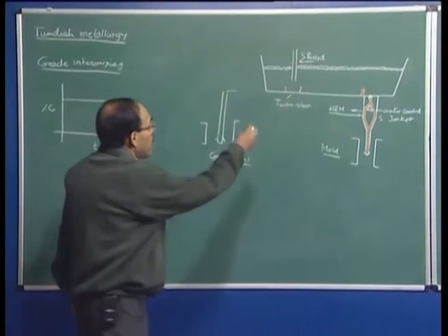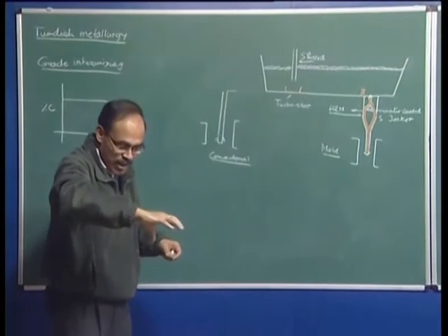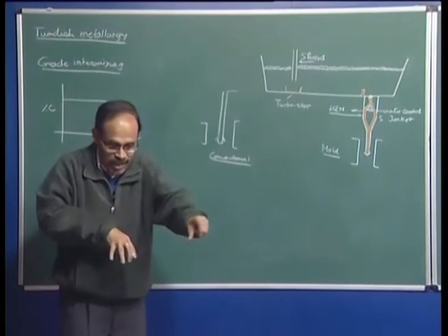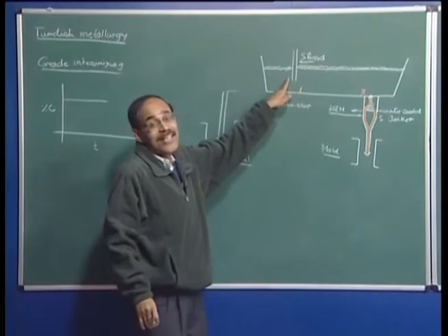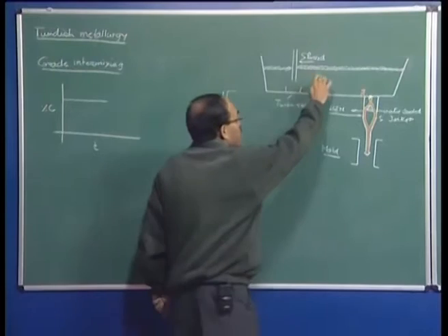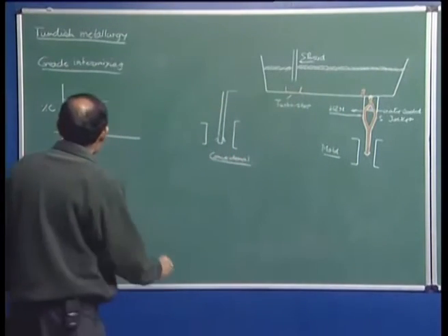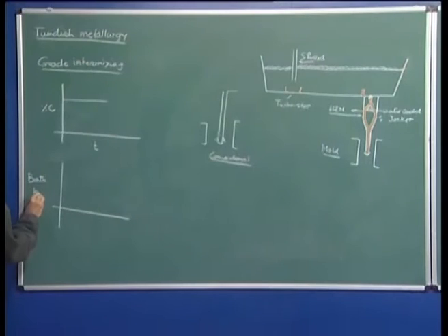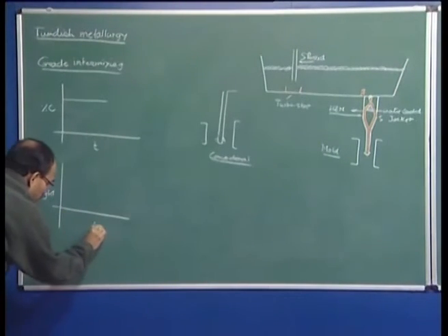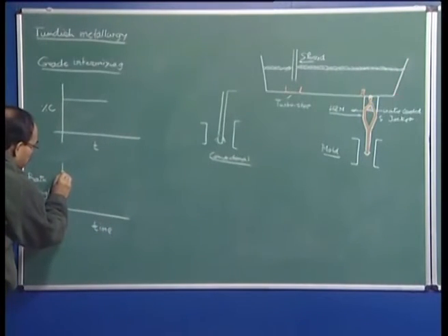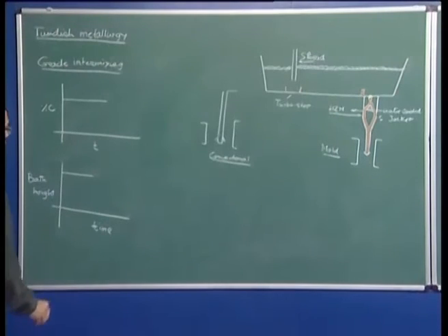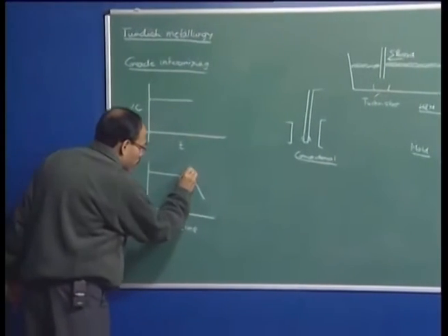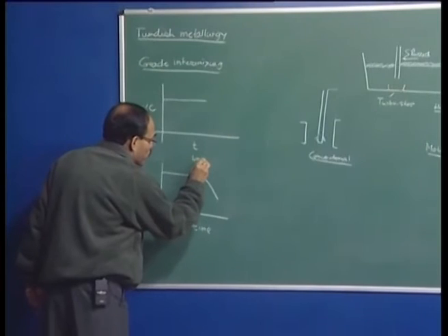Now, when you withdraw this ladle, for this particular time there is no material flowing into the tun dish, so this particular ladle is exhausted and it undergoes rotation like this. So, for some time no material is coming into the tun dish, as a result of which the bath of the tun dish is going to go down. If I look at the bath height versus time, the bath height remains initially constant and then at a certain point of time starts to fall, and I can understand that this is the time my ladle is removed.